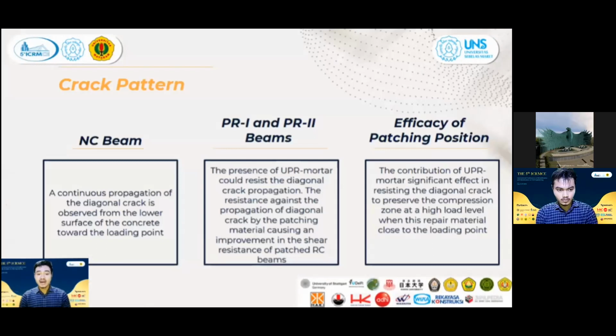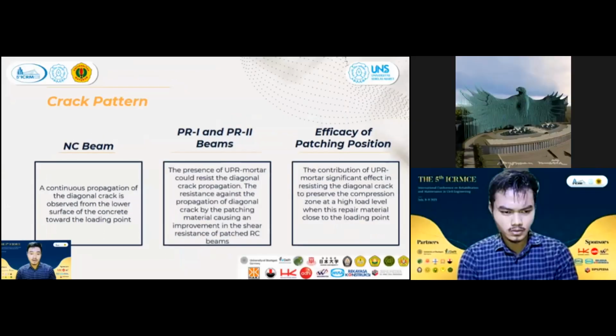And I will explain the mechanism of the crack pattern on each specimen. In the NC beams, a continuous propagation of the diagonal crack is observed from the lower surface of the concrete toward the loading point. While in the PR1 and PR2 beams, the presence of UPR mortar could resist the diagonal crack propagation. The resistance against the propagation of diagonal crack by the patching material causes an improvement in the shear resistance of patch RC beams.